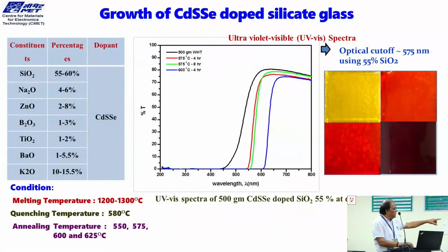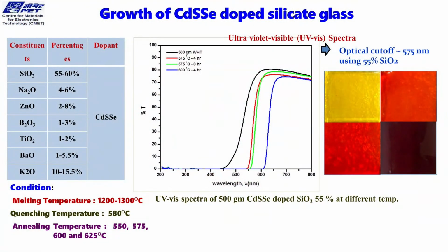You see this, because of the particle size, you can get different colors, because what happens with electron and hole recombination suppression depends upon the quantum size quantization effect. Suppose this yellow glass may contain 2 nanometer particles, that red glass may be 4 nanometers, and this black is 6 nanometers. So with size, the same compound can give four different optical properties.